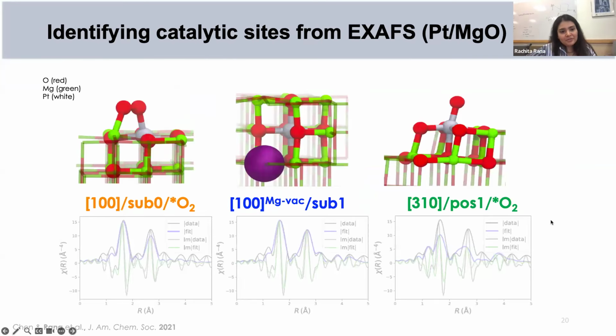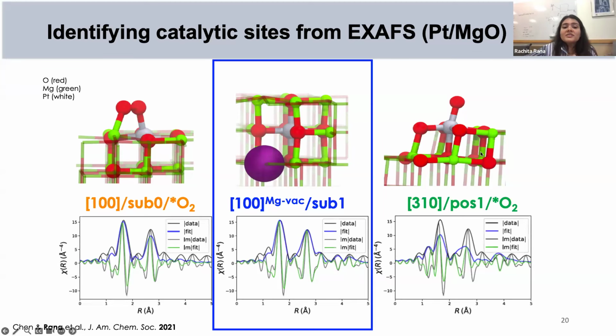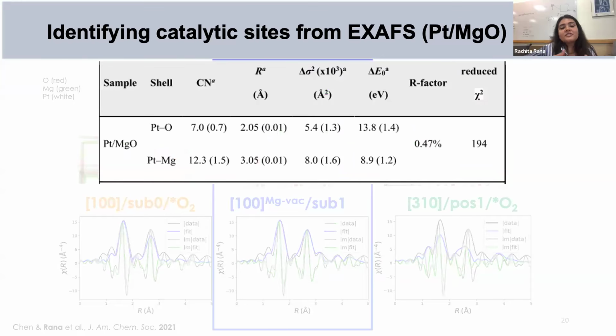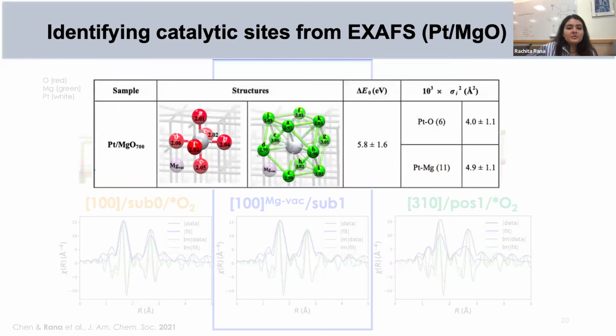So let's see what the structures look like first. The first one was a surface platinum that was bound to two oxygen species. The second one was a subsurface platinum that was embedded inside the magnesium oxide lattice and was adjacent to a magnesium vacancy. And then the third one was a step site. And indeed, the 100 Mg vacancy structure gave us the best EXAFS fit, as you can see here on the slide. Moreover, instead of having those average coordination numbers that we always struggled with, particularly for these atomically dispersed sites, we were able to map what were the nearest neighbors to our platinum atom. And that really helped us in further calculating barriers and other things that I will show you shortly.